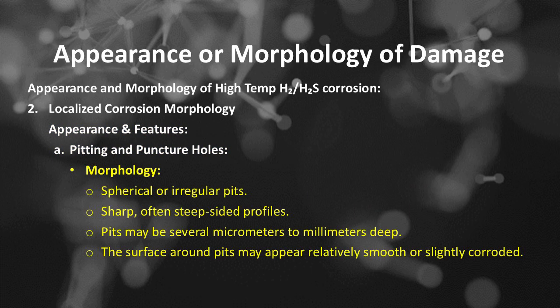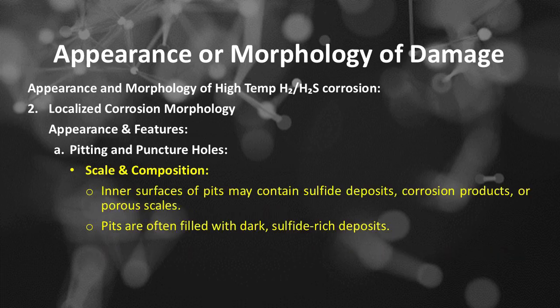The morphology of pitting and puncture holes: spherical or irregular pits, sharp, often steep-sided profiles. Pits may be several micrometers to millimeters deep. The surface around pits may appear relatively smooth or slightly corroded. The scale and composition of pitting and puncture holes: inner surfaces of pits may contain sulfide deposits, corrosion products, or porous scales. Pits are often filled with dark, sulfide-rich deposits.